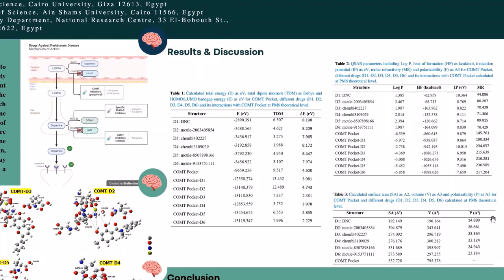We did a QSAR analysis by calculating electronic descriptors like energy gap, hydrophobic descriptors like the partition coefficient, and also steric descriptors like molar refractivity. From the results, we can conclude that there are two promising drugs that penetrate the blood-brain barrier, having more stable interaction with the enzyme compared to the original drug, and have larger gap energy than DNC. Thus, they are less reactive toward the surroundings, and they can also fit into the pocket according to volume and surface calculations. Thank you.